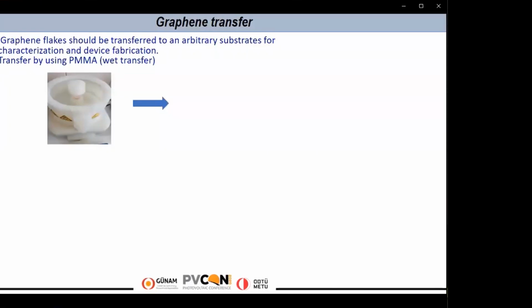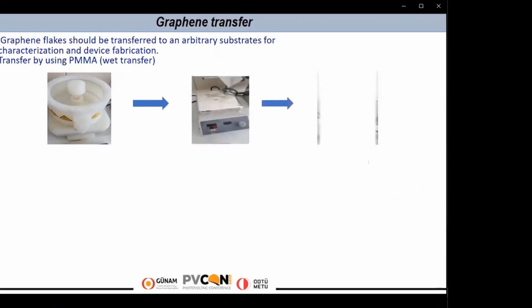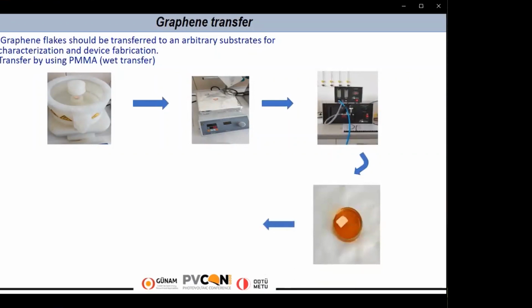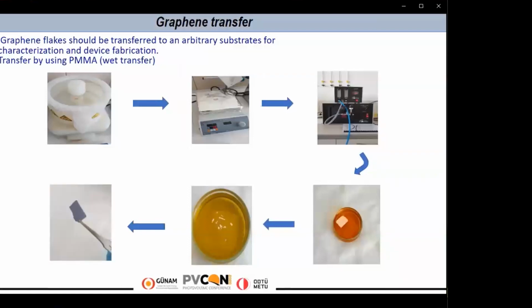To begin, copper was coated with PMMA by spin coating. Then the copper was baked on the hot plate for a few minutes. After that, we clean off our copper backside in the plasma cleaner. Then we etch away the copper with etchant, iron chloride. In this figure, PMMA and graphene are floating on the iron chloride etchant. Then we can transfer our graphene to any substrate.